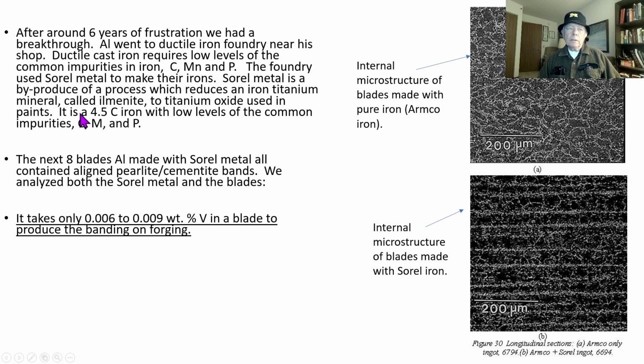The byproduct is a 4.5% carbon iron with very low levels of the common impurity elements, used in these ductile iron foundries. So Al made 8 blades. Here's what we found after the first one. Here the blade is with the sorel. Here's a blade made just the day before with no sorel, pure iron. And you can see, bingo, we're getting alignment when the sorel is used.